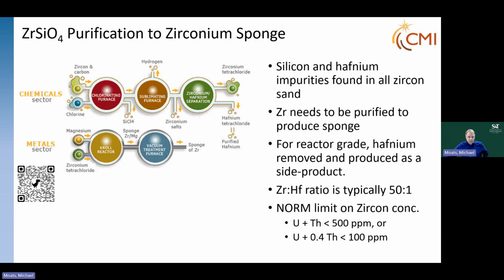The other thing I think that's important to realize is that the zircon industry has limits on NORM. NORM means naturally occurring radioactive materials. And so there are two specifications quoted in the literature: that uranium plus thorium has to be less than 500 ppm, or that uranium plus 0.4 times the thorium concentration has to be less than 100 parts per million. And that, of course, means if you're going to start dealing with zircon to create zirconium or zirconia, you have to be careful about the resource, the material that you're getting. Naturally occurring zircon may be slightly radioactive, and you have to be careful of that.